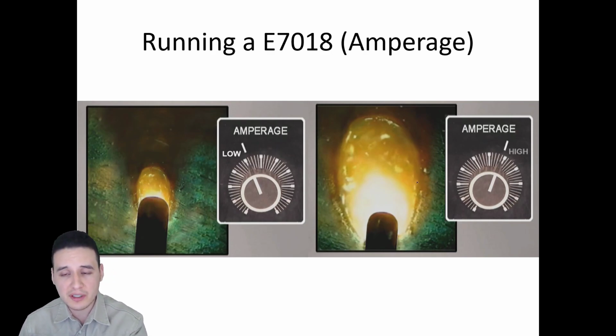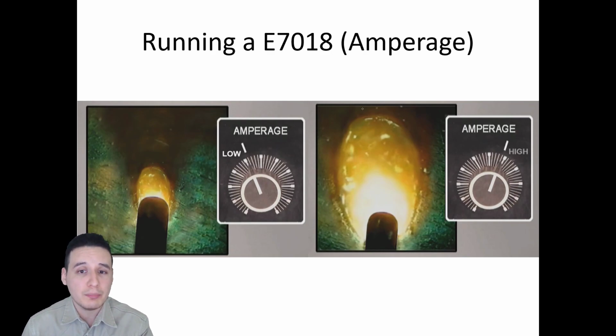On the opposite end, if you're welding too hot, you're going to have that weld puddle being way too big. Notice that in this illustration, you can kind of barely tell where the edges of the weld are at. So your edges are about somewhere in there, it looks like, of the actual bead itself. And so notice the weld puddle is just as wide and big as the bead itself. You never want that to happen.